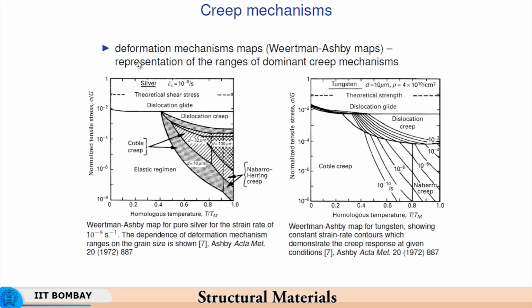So, now we see here different creep mechanisms based on what are called Weertman-Ashby maps, and for different materials, for example, here we take silver, which is a face centered cubic, tungsten is a body centered cubic material, and we have different mechanisms of creep operating at different conditions. So, you have normalized tensile stress, and you have different homologous temperatures. So, homologous temperatures range from 0 to 1, and you have what is called as Coble creep at relatively low stresses, and you see that the Coble creep starts at relatively lower temperatures as well, and dislocation creep is also present even at relatively higher temperatures and relatively higher stresses.